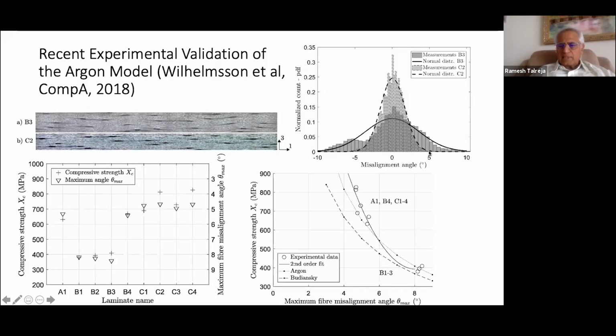And they were plotting the misalignment angle with its frequency. Then we're fitting Gaussian curves to that, going to a very high level of probability, 95% or so, and picking up that angle. That's the maximum misalignment angle they were using in Argon's formula, and finding excellent correspondence with the data, the compression failure data.